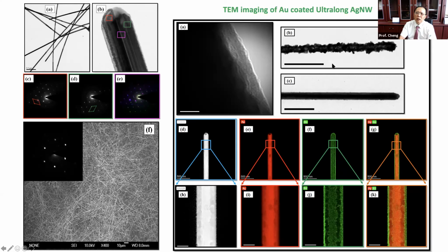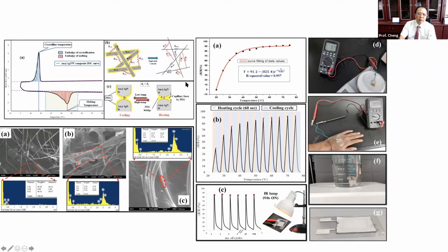We also did the oxidation test with H2O2. Without any gold coating, you can see the silver is already oxidized. But with gold coating, there is no oxidation with H2O2. And after the DSC test, you can see our material's Tg point, the melting point, is around 45 degrees. That means the sensing range will be 25 to 55. It's quite sensitive because when the PEG melts, the wires come closer. The distance between two silver nanowires will be very close by the capillary force. Then the conductance will increase.